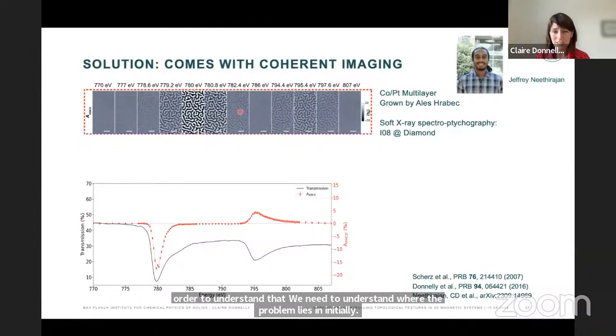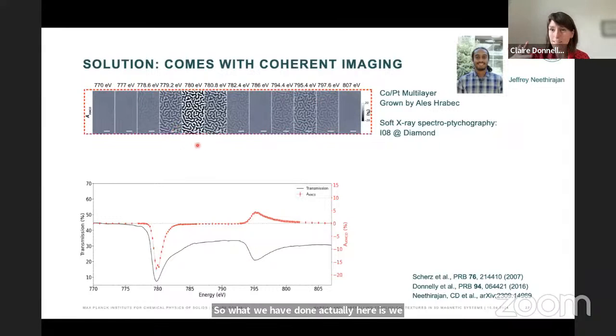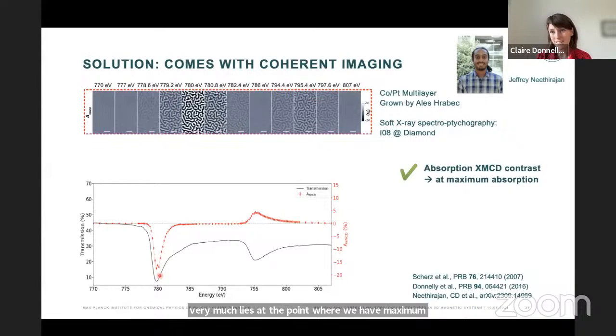So what we have done here is we've performed some spectral ptychography, so we gain access to our complex spectrum. And we can already see the issue: our absorption XMCD very much lies at the point where we have maximum absorption of our sample. What this means is that XMCD imaging is typically going to be limited to thin samples, which are not so highly absorbing as thick samples.